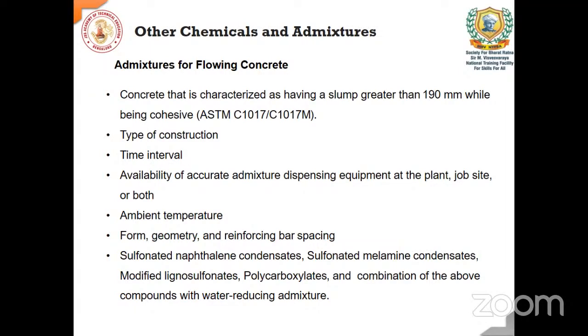Now, to achieve the flowing of concrete, I gave the example of Burj Khalifa, where the world record as on date was 606 meter. The concrete has to flow like water. To achieve that, we need to add a combination of admixtures. It can be an air entraining agent, water reducers in the form of superplasticizers, retarders. It is a combination of admixtures. If I say it is a flowing concrete as per ASTM C1017, it should have a slump of more than 190 millimeter.